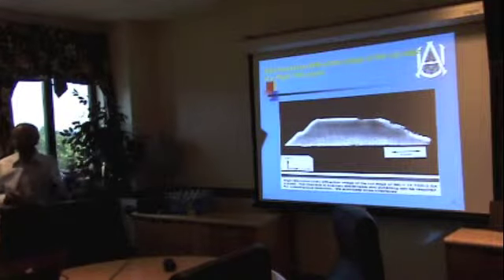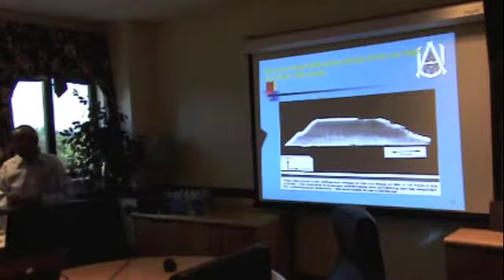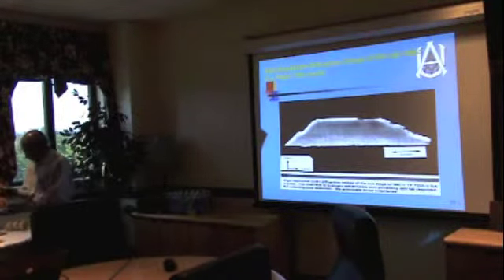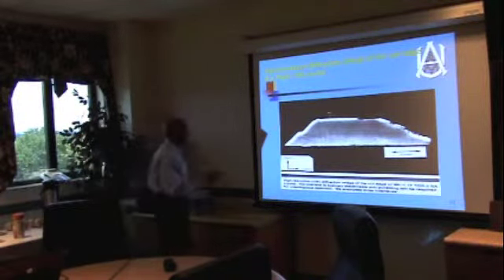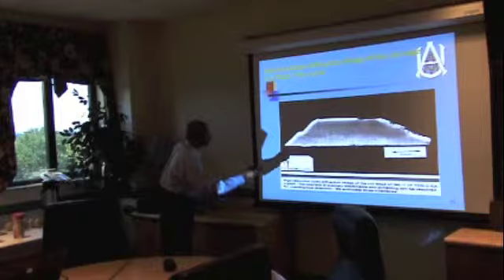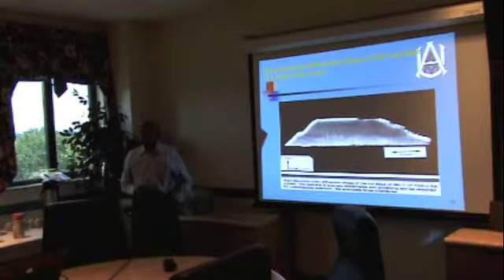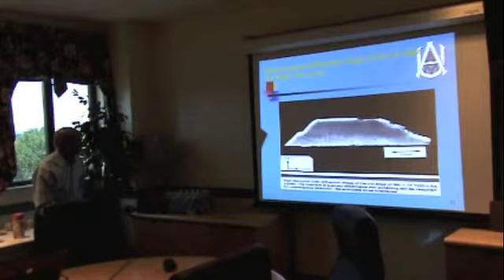This is an interesting picture. This is an actual slice cut from the flight grown crystal of IML-1. If the growth was, for example, here, we cut a slice parallel to that face, and somewhere here should be the seed crystal, and then the new growth is up here. So if I use X-ray diffraction technique, I should be able to locate if there is a crystal grown on the ground. I should be able to see the growth interface right at this point. But in this slice, we could not locate it.